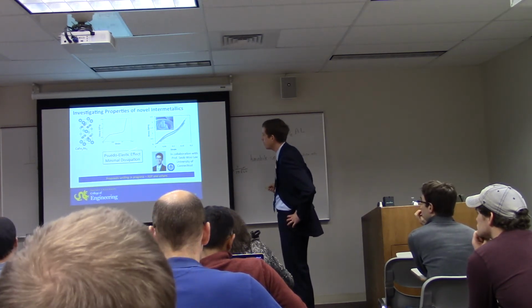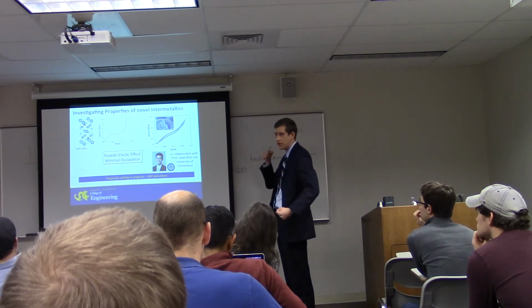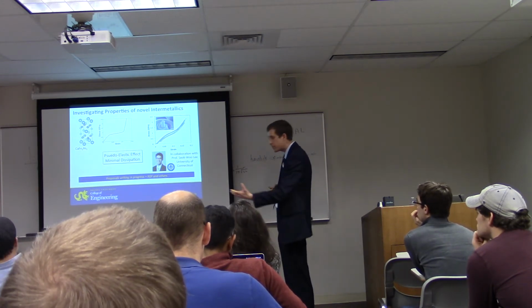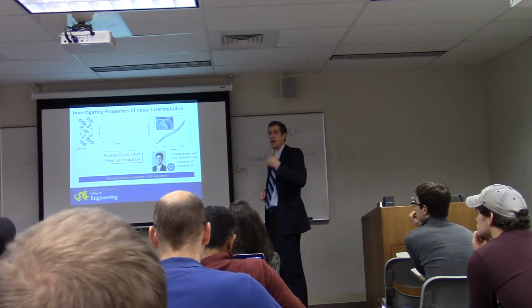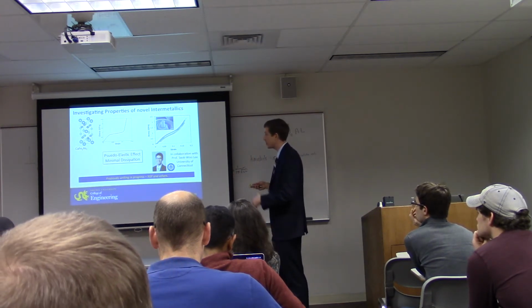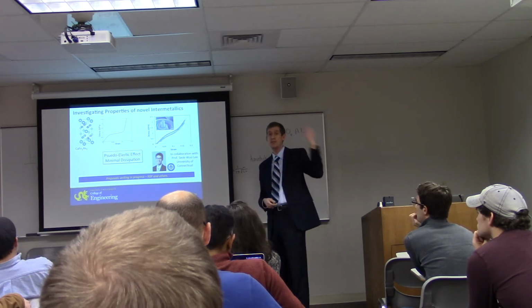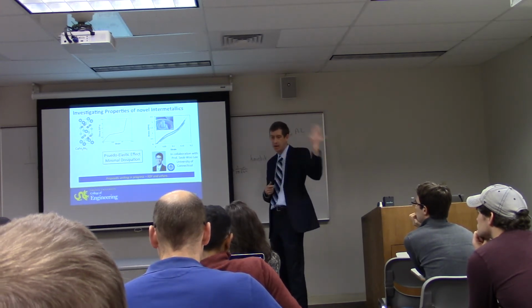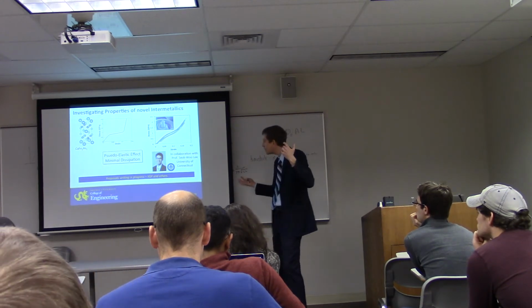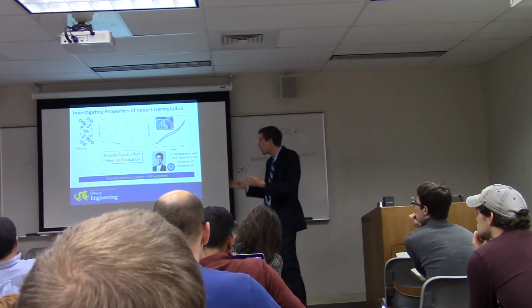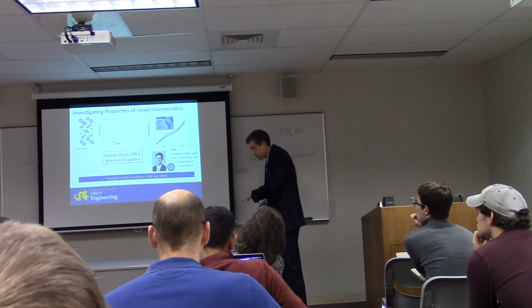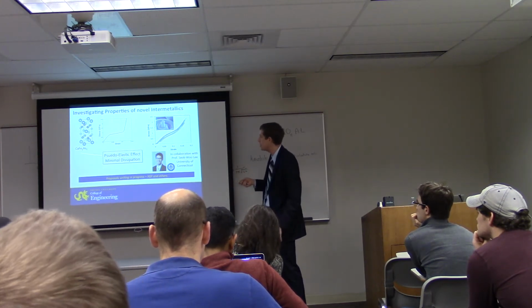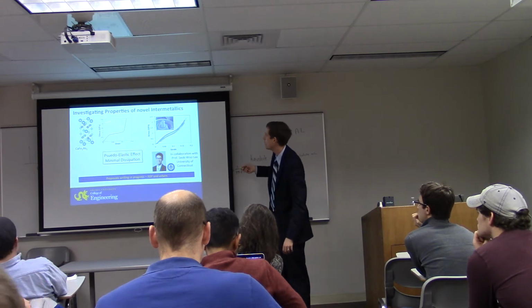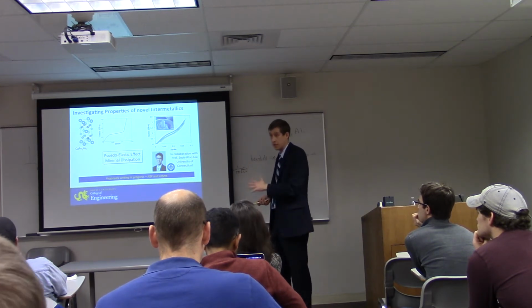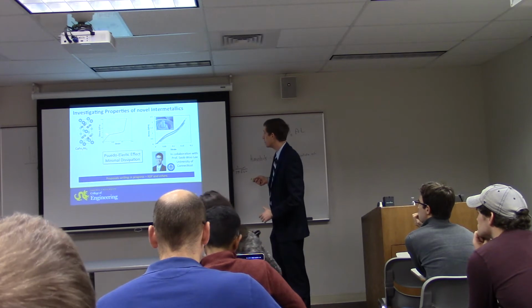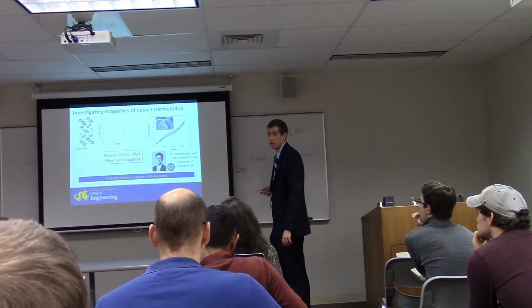We can actually model this with a combination of DFT, so I can strain fundamentally the unit cell. I can wrap this up into micromechanical theory and thermodynamics because it's going to split into phases as I deform. Some of it's going to be high temperature phase, antiferromagnetic, and the other half is going to be non-magnetic, whatever. The point is we can couple thermodynamics, microstructural modeling, and the input of the DFT to produce a stress strain curve that, for as simple as the model is, gets transformation stresses and strains that are very close.